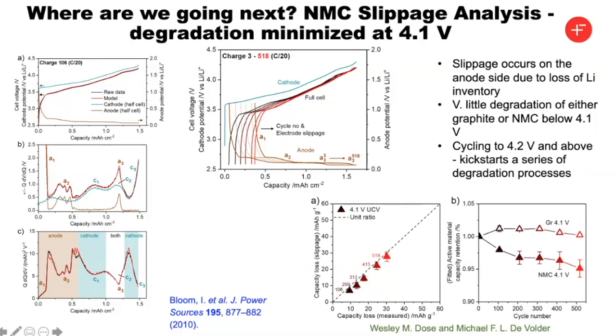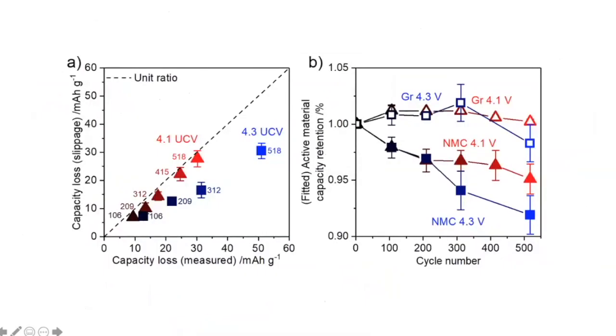And this is what's shown in this so-called slippage curve, where you're plotting the capacity loss versus the capacity, so the slippage on the anode. And so this is all good to 4.1, but when you now start to move above to 4.2 and 4.3, and you start to see the processes that I was describing with these fatigue phases, then you start to see additional processes coming in from the cathode starting to degrade.